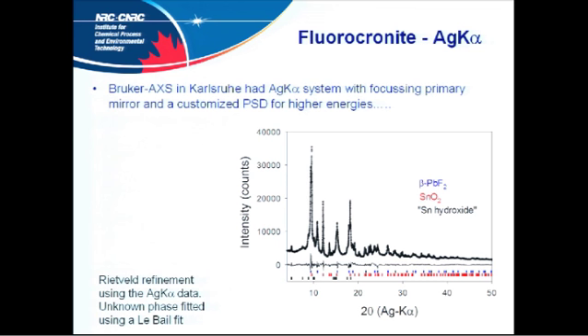And they've also got a customized PSD for the higher energies, because silver is a high enough energy that most PSDs won't even pick it up. Or even if it does, the actual efficiency is going to be horrendous, because most of the radiation just goes straight through. So there are such things as customized ones, and this is basically a Rietveld fit of these two phases, and this is yet another.